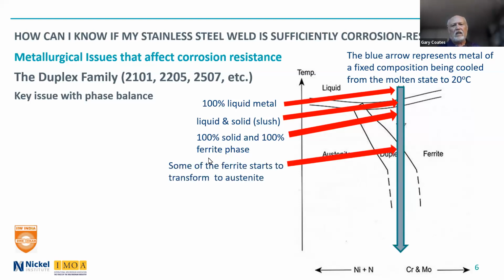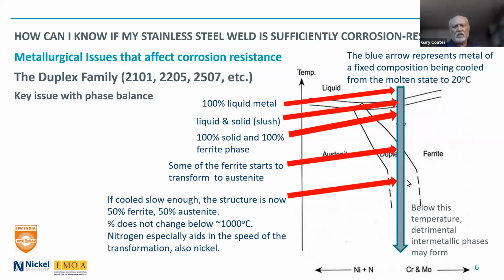And if it is cooling down slow enough, some of that ferrite starts to transform to austenite. And once you get to about 1,000 degrees C, if you've done it slow enough, you will have a structure close to the 50-50 austenite-ferrite range that you want. Nitrogen aids in the speed of the transformation, which is why nitrogen is extremely important in the duplex alloy. Nickel also does that. But once you get below 1,000 degrees C, if you have too slow a cool, you can get intermetallic phases that form, and this is one of those things that is very difficult for welders to understand. So it's really something the welding engineer has to get through in his own head.